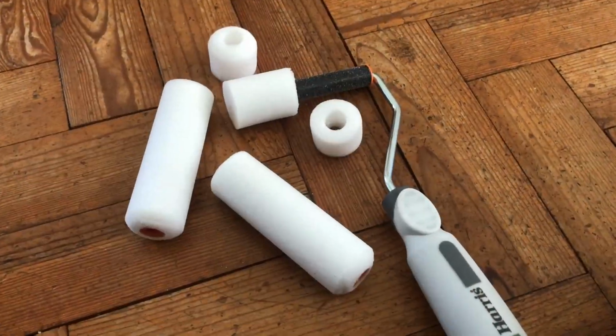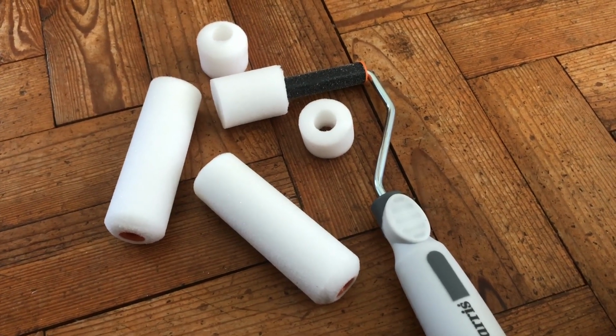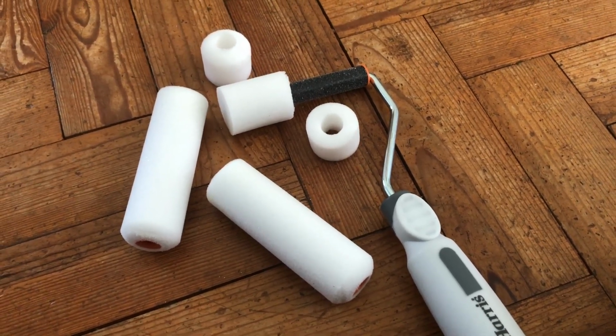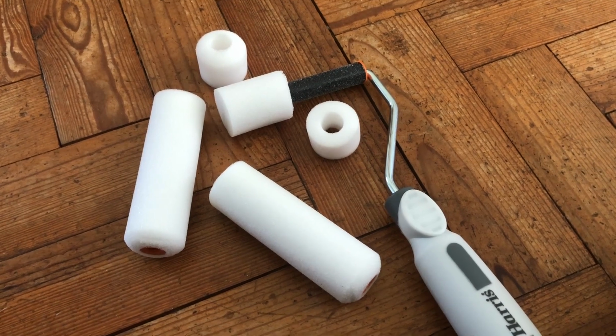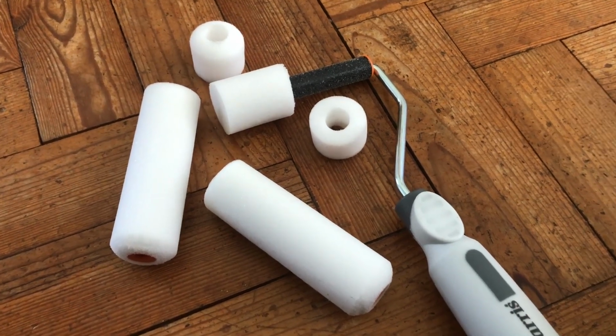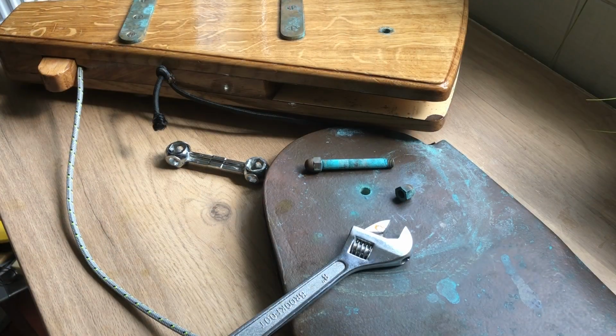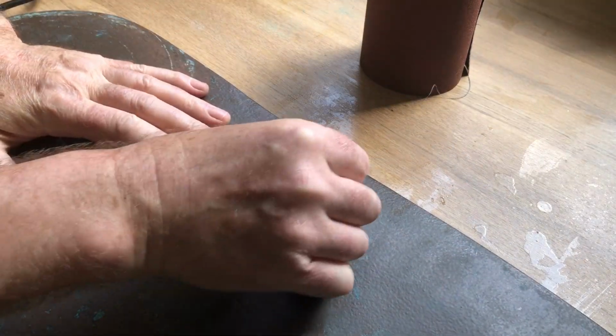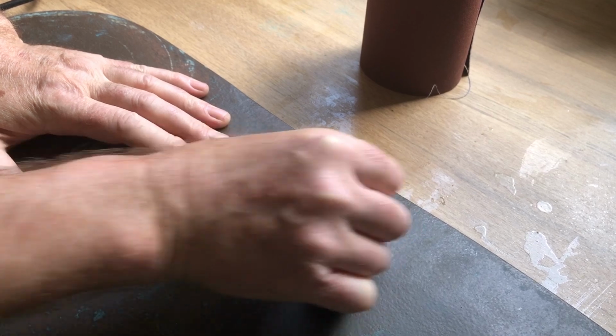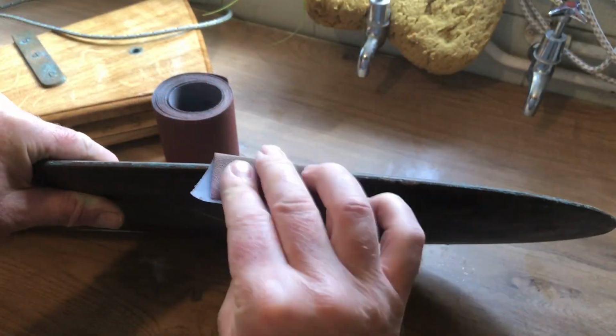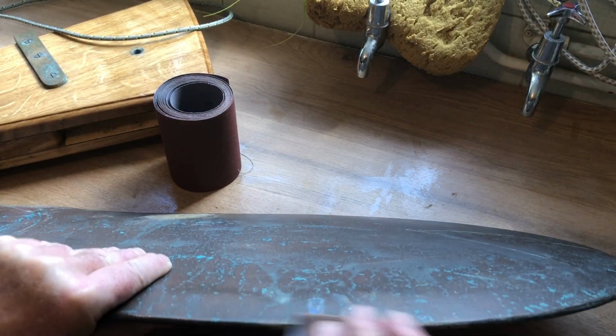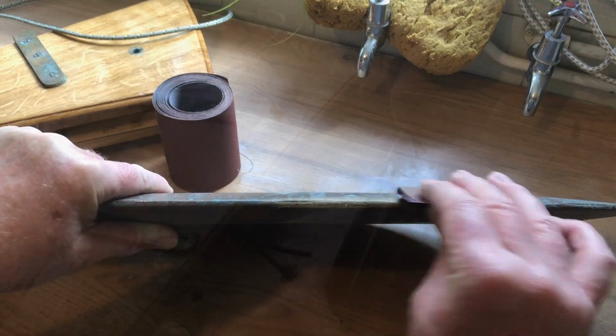The sections of the rudder blade that needed touching up were small, so to avoid wasting precious Coppercoat, I cut my foam rollers to reduce their surface area. After detaching the blade, I prepared the surface. To ensure the new coating bonds well, Coppercoat recommend using 80 to 180 grit sandpaper to remove any green powder-like verdigris.